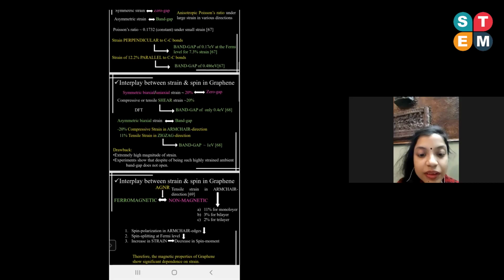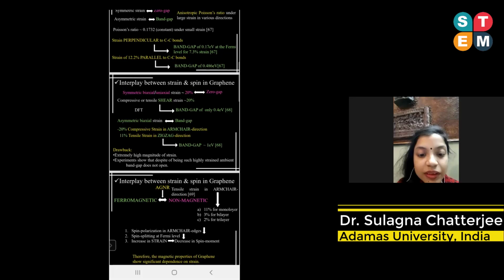However, for compressive or tensile shear strain, so we may consider it to be a bit asymmetric, of the order of 20%, only 0.4 electron volt of band gap may open up. Asymmetric biaxial strain leads to band gap opening. Minus 20% of compressive strain in the armchair direction and 11% of tensile strain in the zigzag direction reportedly opens a band gap of 1 electron volt. However, the magnitudes of the strain are very large, and experiments show that despite being under a strain state as predicted by the DFT calculations, the expected amount of band gap does not open up in graphene.